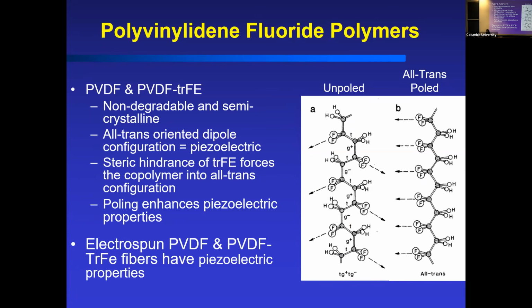They are used quite readily as sutures, but they are non-degradable, which is great for us. We can use them as a model. And they've been well characterized for their piezoelectric properties. And so when they're poled, in this all trans pole position or oriented dipole configuration as shown here, that gives it its piezoelectric properties. So you have those fluorine, you have those hydrogens. Again, when a movement is applied, you get this development of net polarization, development of charge. And so we can use electrospinning, our fiber forming process, to actually pole them, which is also neat.